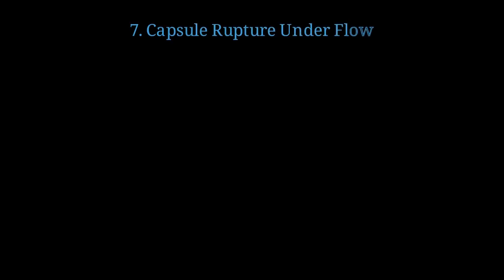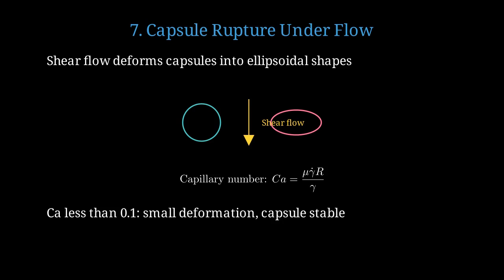Let's analyze how capsules rupture when subjected to hydrodynamic forces in flowing fluids. In shear flow, capsules deform from spheres into ellipsoids, creating stress concentrations. Under shear flow, the spherical capsule deforms into an ellipsoid, with maximum stress at the poles. The capillary number Ca equals viscosity μ times shear rate γ̇ times radius over surface tension. For capillary numbers less than 0.1, deformation is small and capsules remain stable. When capillary number exceeds 1, deformation becomes large and rupture becomes likely. Critical stress for rupture is approximately EH/R, proportional to elastic modulus and thickness.